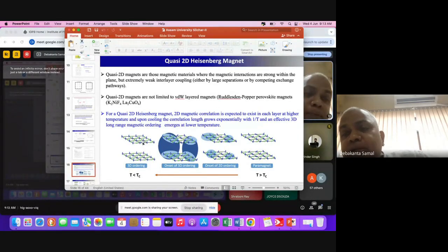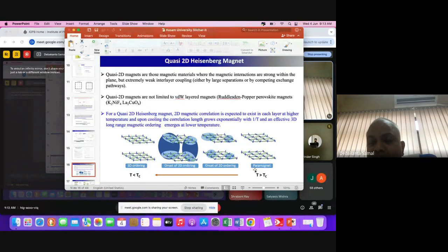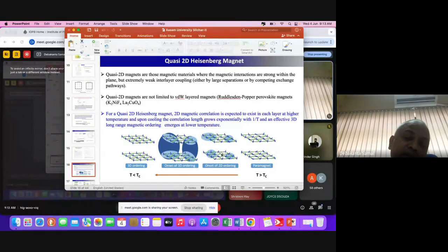This is a very important area of research. And how does the ordering happen in this kind of material? At T greater than Tc, all spins are randomly oriented. This is a paramagnet. As you are lowering the temperature, in each layer some ordering starts. This was completely random paramagnet, and now as you are cooling, some ordering starts here, and also some ordering starts in the next plane. And what happens when you cool down the temperature again? The coupling between the bottom layer and the upper layer starts, and finally you will have a magnetic ordering. This is how the quasi 2D Heisenberg magnets order.